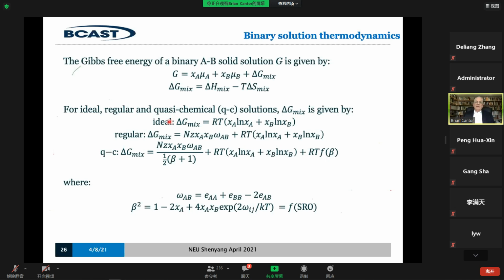Now, most materials aren't ideal. There is some enthalpy of mixing, so in a regular solution, the enthalpy of mixing is not very large, so the entropy is still this, it's the same. And if we have a more realistic quasi-chemical or other, then there's the enthalpy of mixing, it gets more complicated. We still have this configuration entropy of mixing, and there's some additional entropy terms. But all we need to think about is there's enthalpy of mixing, and there's some configurational entropy. We don't need to worry about what's called the excess entropy too much.